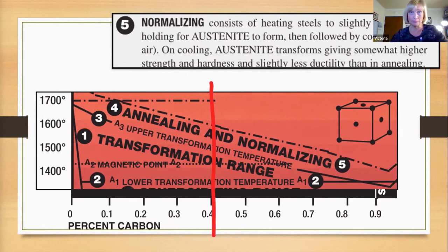The other thing, and to me, this is the bigger factor, is that the magnetic point is right here at the 1420 range, which you've probably already noticed is below our upper transformation line and below our annealing and normalizing line, which is about 150 degrees. So no, the magnet doesn't tell us when we got here. What it does do, and I would recommend you use the magnet for, is to start to learn what color your metal is in your forge, or maybe even a new forge, when your metal goes into that transformation range. That's what the magnet tells you. It tells you how to read that color.